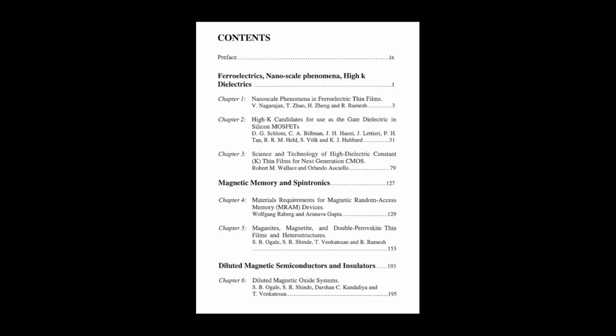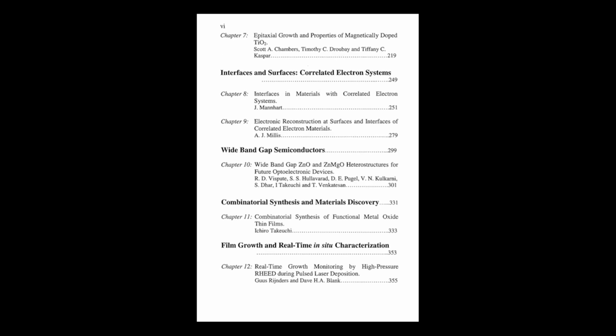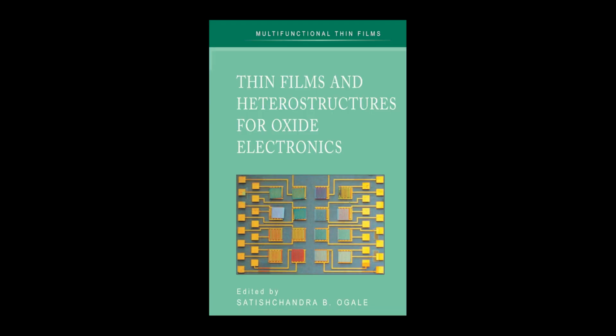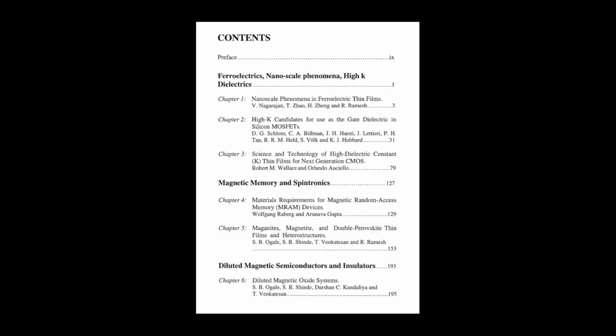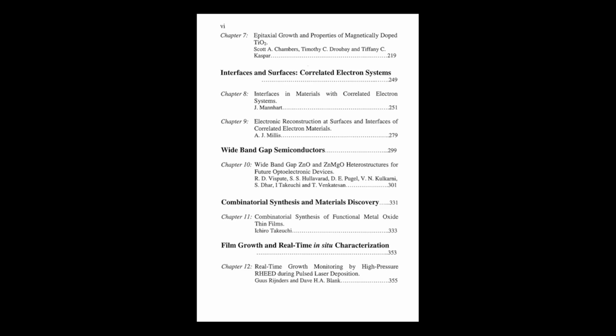Makes sense. Now, beyond just pure ZnO, researchers often need to tune the electronic properties, like the band gap. Alloying is the usual way, right? Right. For ZnO, they looked at alloying it with magnesium oxide, MgO, to create ZnMgO alloys. Adding magnesium pushes the band gap wider, potentially up to around 3.9 eV, useful for tuning the color of light emission or detection. Another problem. Alloying isn't always straightforward. Not here, no.